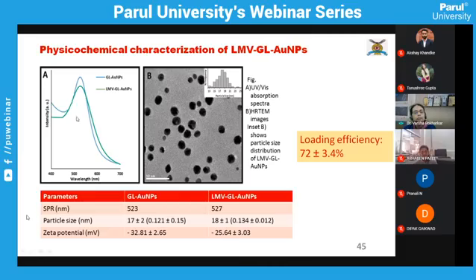So here again you can see the UV visible spectra. The blue is for the glycyrrhizin reduced gold nanoparticles, and the green curve is for the lamivudine loaded gold nanoparticles. The lambda max remains the same with a decrease in intensity, which is quite obvious because the surface of the gold is now covered further with lamivudine. And this is the HRTEM image, which indicated that there is not much change in the size after loading of the drug onto the nanoparticle surface. You can see the SPR band at 523 for the glycyrrhizin reduced gold nanoparticle, and not much shift after loading of the drug. The particle size also has remained pretty much the same.